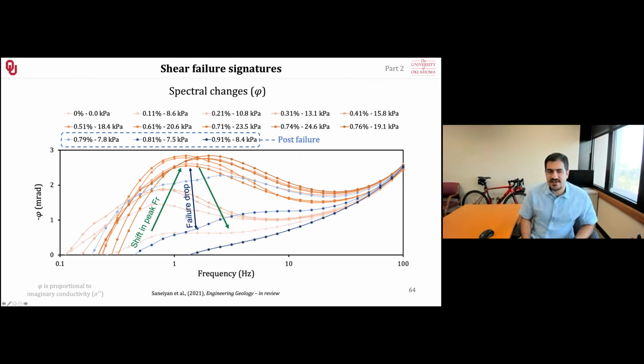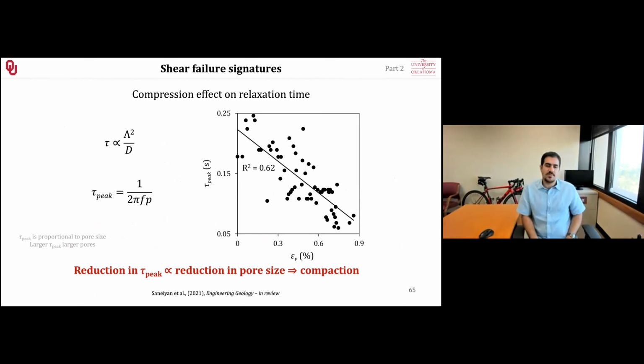We can also clearly see this in our phase signal, which is good for field measurements. Initially, we have a peak below 1 hertz, it increases in magnitude, and then at the failure point it immediately decreases. We are also clearly seeing a trend from lower frequency to higher frequency. That means our pores are getting smaller, so the time constant is going towards shorter times. If we plot the relaxation time constant, basically the time it takes the ions to diffuse back after being polarized, we can see that it is reducing over time. It shows that we have compressed the sample and reduced the pore sizes. Initially they were microns in size, and now they are much smaller because of the compression.